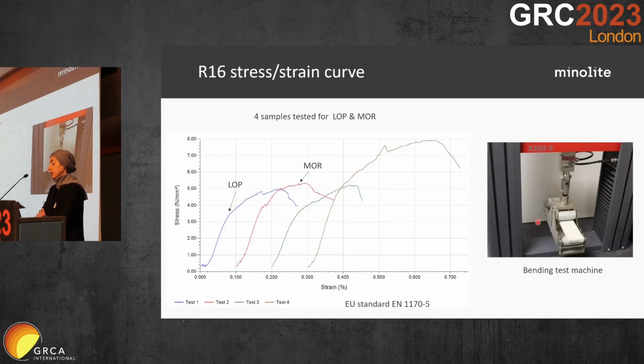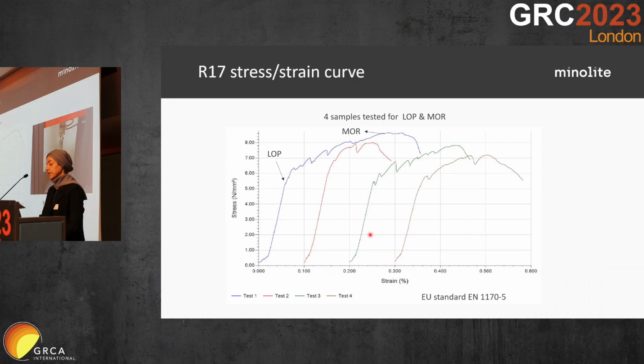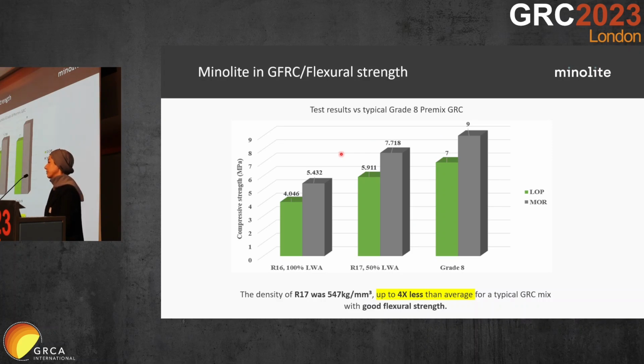We have done the bending test, or external labs did that, and we have done 4 different tests for one sample. You can see the R16 stress strain curve here, following the standard EN 1170. And this is for R17, in which 50% Minolite was used. You can see the higher MOR and LOP. And this is the comparison between them.